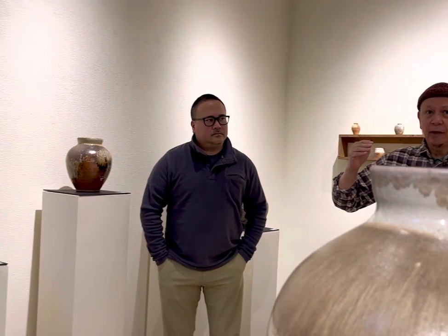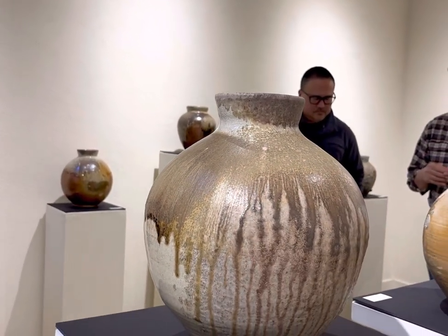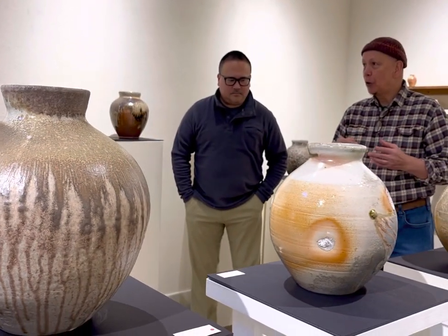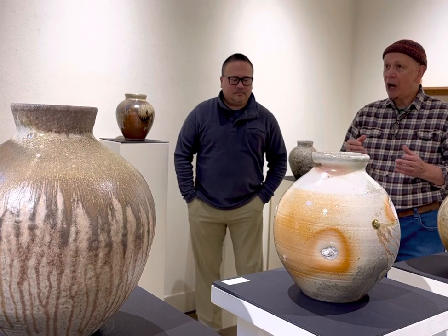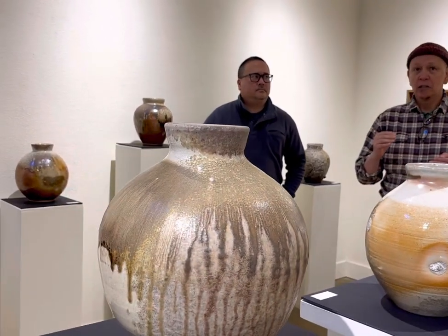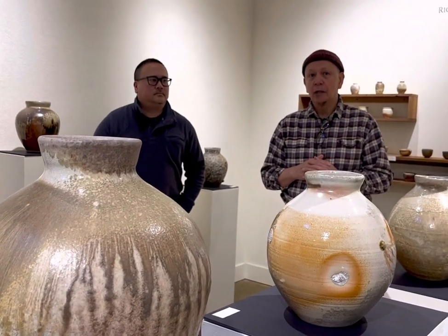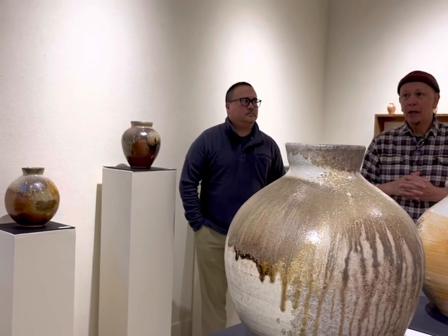Maybe a little. In the anagama process, it's pretty natural to form the curve of the firing, and the curve kind of looks like a bell curve, and so we try to keep it within 150, 200 degrees per hour firing, and so we follow that natural curve that's formed with the wood burning in the kiln. And so we fire it up to 2,400 degrees Fahrenheit, and we hold it there for about 40 hours. So that's what happens. We use about 15 people in the last firing.